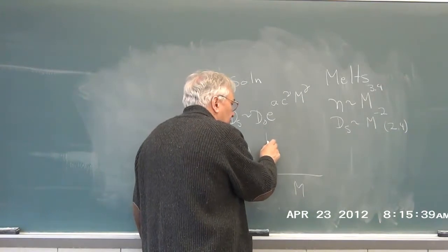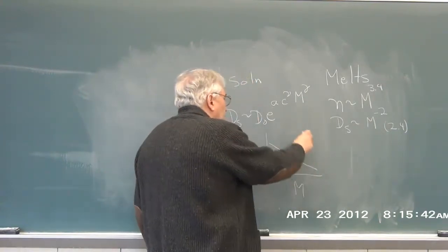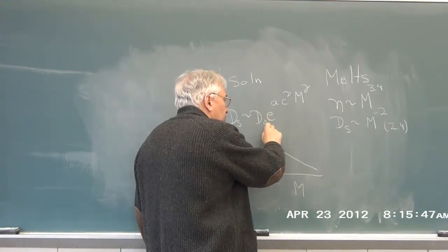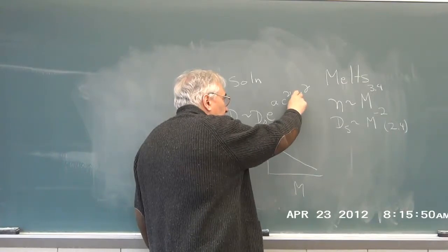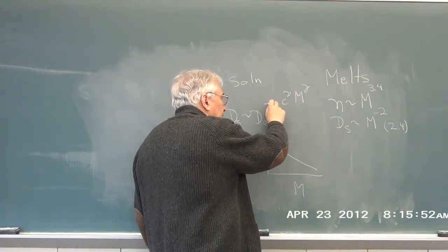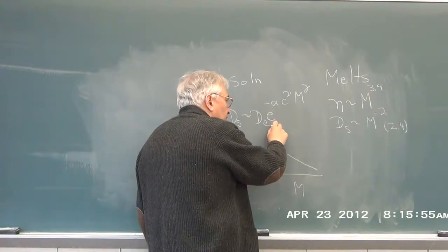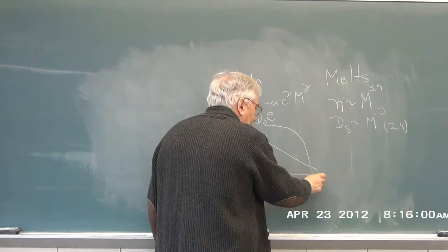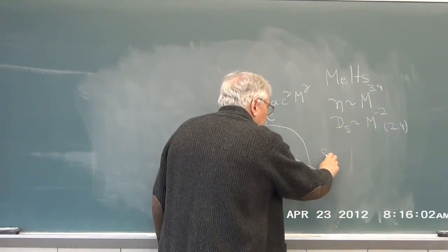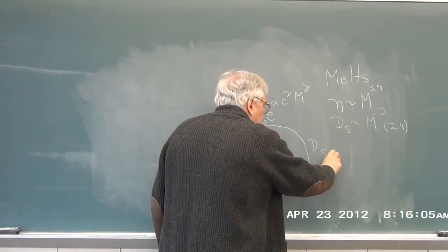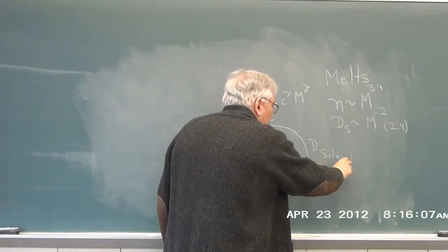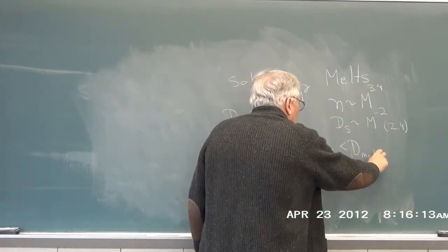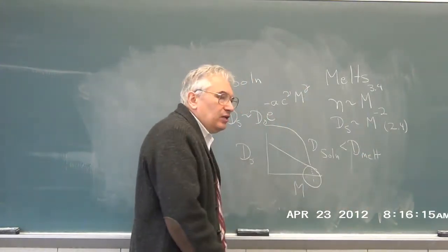here's the self-diffusion coefficient in the melt. Here we are in solution, and we would typically say that diffusion in solution might be faster, but this function is going to fall, I'll make a positive number, as an exponential, and therefore at some molecular weight, you would say that ds in solution, if you just extrapolate the function, would be less than d in the melt. Well, that's an unreasonable outcome. At least most people would agree it's unreasonable.